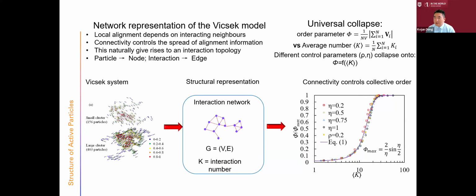So we use network analysis. Not only the neighbors, but also the clusters, to describe the Vicsek system. And very interestingly, we found that with a structure descriptor, the average connectivity, we can uniformly correlate the structure with the order parameter, which is how uniformly all these particles fly in one direction.